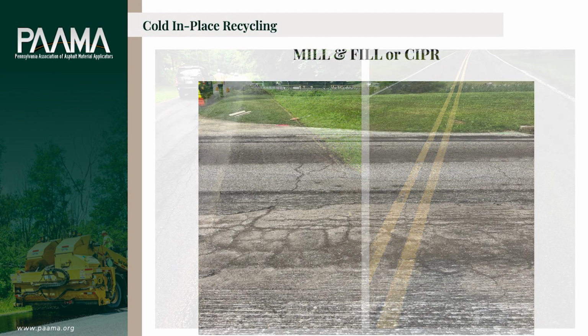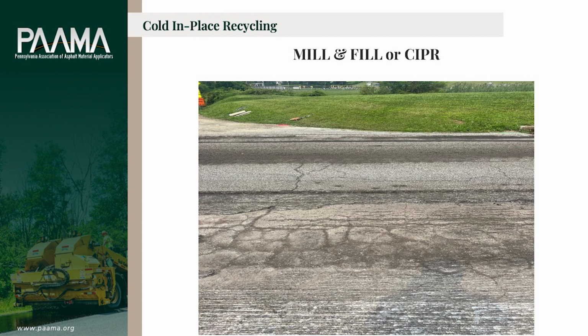Now, when we look at mill and fill, when you're looking at this particular roadway, one section has already been milled off and you see the corrugation on the bottom, and of course all the cracks that were there have been filled in by the fines from the milling operation. Now, do we ever go in and scrub those cracks open and then crack seal them? No, we go in and we pave right on top of what we see there. You'll see the crack in the center there that's coming across the roadway, and you can follow that crack all the way through up to the corrugated area.